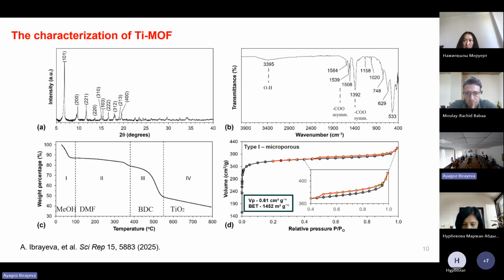From the BET analysis, what model did you use for the calculation of average pore size and pore volume? In the core facilities at Nazarbayev University, we give our powders to engineers, and they send us the ready analysis. This BET data was in TXT format, already calculated by the equipment. We just plotted the relative pressure of this material. Okay, so not all parameters are shown in the slide. For example, pore size is also a main parameter. You just tell us that it is micropores. Yeah, briefly.